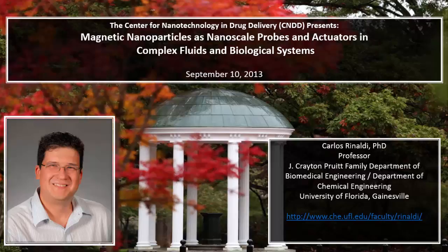What we see, very similar to the measurements with anthracene molecules, is that below a certain molecular weight, there's very good agreement. The Stokes-Einstein equation applies. And above a certain molecular weight, there's a divergence between the nanoscale viscosity and the viscosity felt by a rheometer. And I don't have the time to go into the details, but an important point is that these are polymer grafted particles, and their hydrodynamic diameters are on the order of 25 nanometers. So the mechanisms that the prior work with cadmium selenide particles claimed would be responsible for the breakdown of the Stokes-Einstein equation are not applicable here. So there's something else going on, and we're actually looking to see what it is.